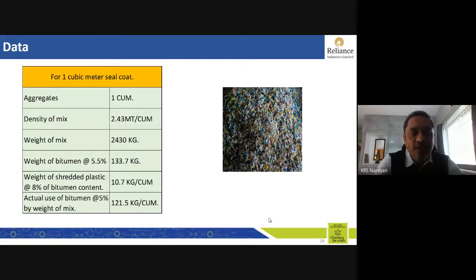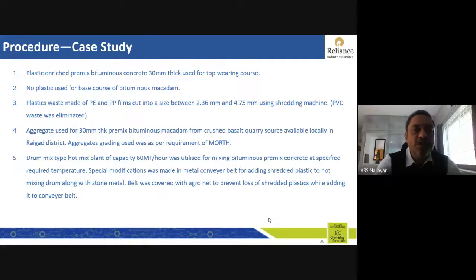2.43 tons of the weight of mix. We added 5.5% bitumen and 8% of shredded waste plastic. So we reduced the bitumen content by 10%. So still maintained 5% by the weight of mix as bitumen. And then 8% of waste plastic as per the IRC code was used in this. And then the road was laid as per the procedure which is here.